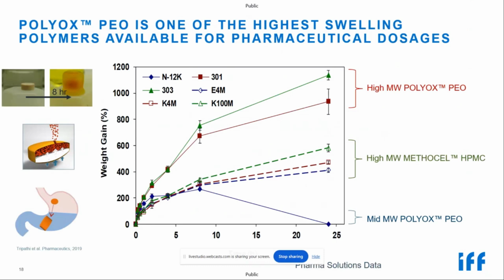All right. One of the most distinguishing features of POLYOX or PEO is the swelling of the polymer. PEO hydrates very quickly and, depending on the molecular weight, swells to many times its original weight. The swelling graph in the center shows pure polymer compacts of both POLYOX and Methocel HPMC. These compacts have been put into 900 milliliters of water, and the weight gain measured over a 24-hour period. These compacts were allowed to erode and dissolve into the medium.